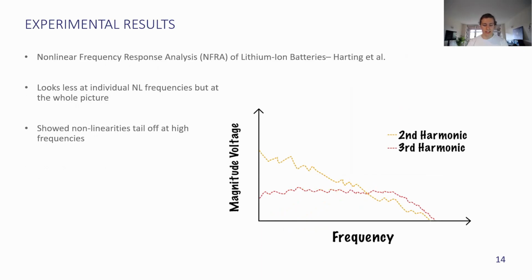And to talk quickly now about some more experimental results from Harting et al. They showed that the magnitude of the voltage response from the second and third harmonics actually falls away as you increase the frequency. And so at lower frequencies then, the nonlinear elements are much more responsive, and at high frequencies, that behavior seems to die away somewhat.